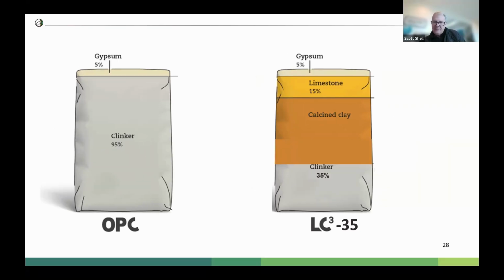There is, however, continued progress on increasing the amount of calcined clay and lowering the clinker content. So LC3-35 with 35% clinker is now a code approved material in some jurisdictions and is being produced in a few plants globally. So this is really driving down the carbon emissions of this blended cement.